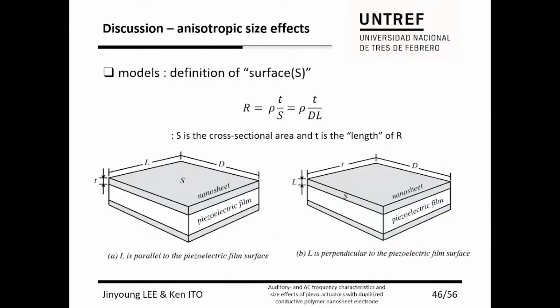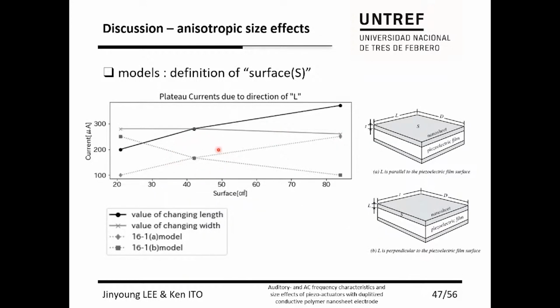We consider the behavior of output based on phenomenological models, with dependence of the resistance value on the electrode area. We can consider the possible situations A and B. The dotted line indicates theoretical model values, and the solid line shows the results of actual measurements. In case A, the current amplitude was enhanced with increasing area, while in case B, it decreased. However, none of the classical models explain our actual measurements, which stay at a constant value with changing width.